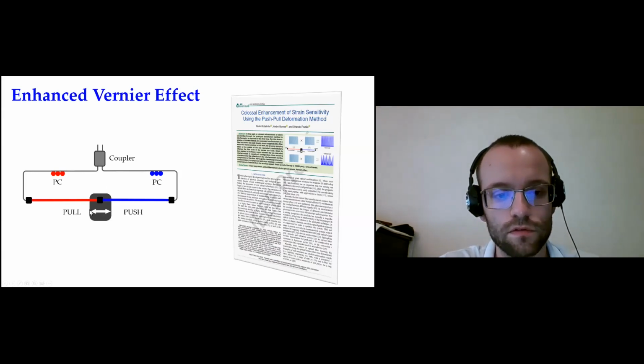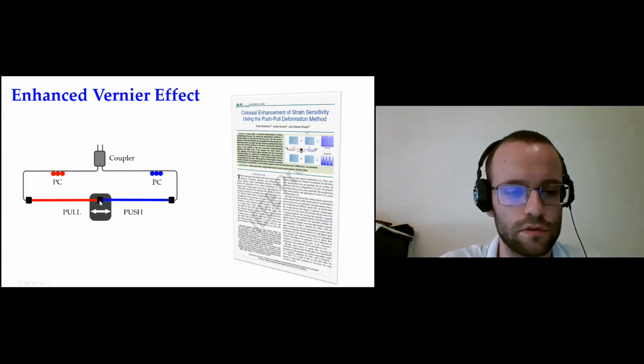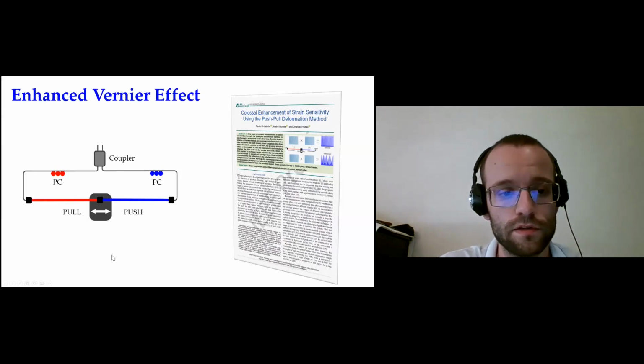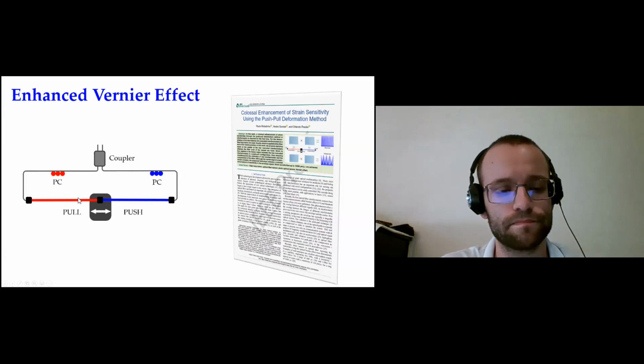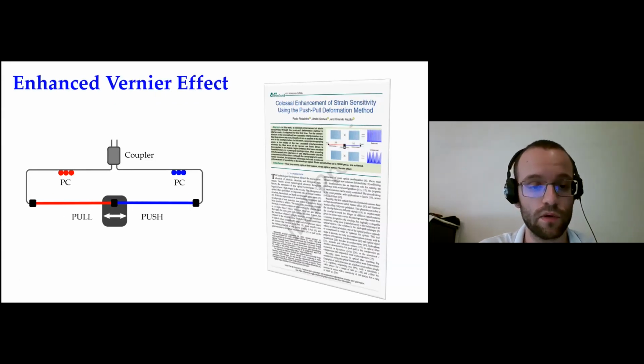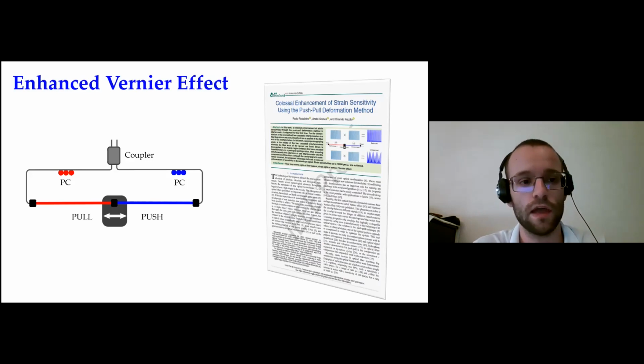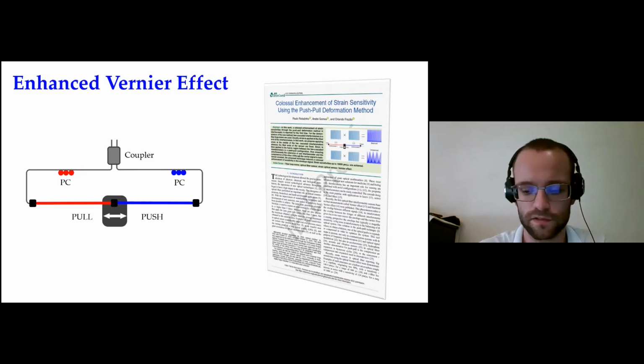When the middle goes to the left, in the red fiber the strain decreases, and in the blue fiber the strain increases. Taking into account that this is the same fiber, since we use two equal bow tie fibers, we have a cavity that moves with asymmetrical movements. So we have a maximization of the enhanced Vernier effect.